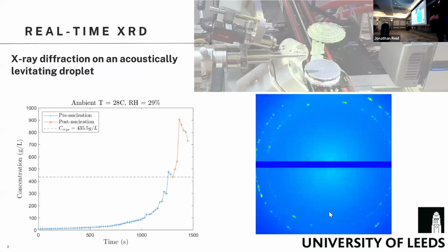Yeah, and actually that's very likely to happen. It's very possible that indeed the crystallization would start on the surface of the droplet, because this is where we have the high supersaturation of the solute. Now, the X-ray beam has a certain thickness, and it would go through the front and back of the droplet. The only thing is that what we will also notice is that due to gravity, some of these crystals would fall to the bottom. Yeah, this is what we've come up with to solve this equation. But indeed, there's a few assumptions taken here.